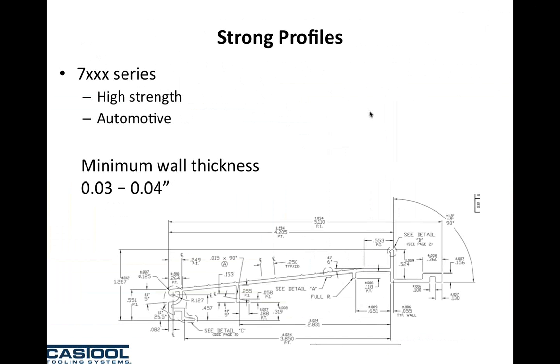But if you go to the other extreme of the spectrum, you're looking for a high-strength alloy, for example, 7000 series alloy. The minimum wall thickness is higher than 6000 and 3000, so that's why you have to use this profile, and then there's a minimum wall thickness you can only extrude through for the strength and the alloy that you want to get out of it. What's interesting is the minimum aperture or wall thickness that you can extrude through the die is also very similar to the gap between the dummy block and the liner. So the gap between your dummy block and liner at temperature during operation is virtually identical to the die aperture.